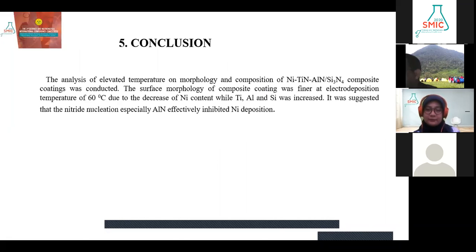The surface morphology of the composite coating was finer at an electrodeposition temperature of 60 degrees Celsius. The finer morphology was due to the decrease of nickel content, while titanium, aluminum, and silicon content increased. It was suggested that nitride nucleation, especially AlN nucleation, effectively inhibited nickel deposition.